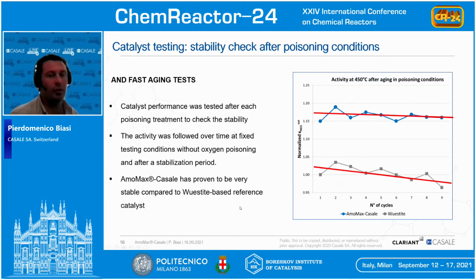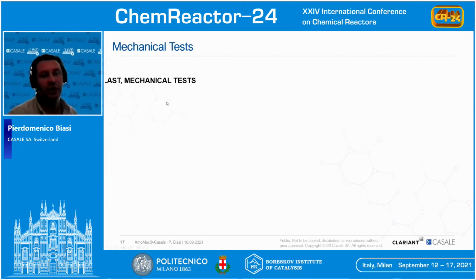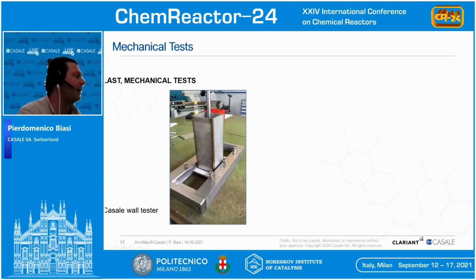But when you implement a new catalyst with a new formulation in the reactor, you also need to understand the mechanical features of the catalyst. So we developed a tester in the lab for the interaction between the catalyst particles and the walls of the reactor, because when you have shutdown, startup, or when you load the catalyst inside the reactor, you have these interactions that are really important, so as not to break the catalyst.